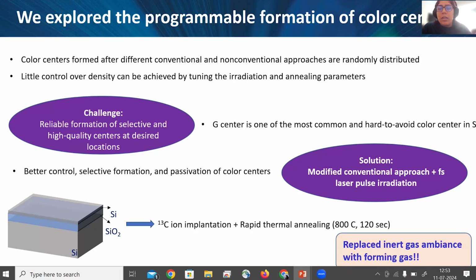What we have done differently is that during the thermal annealing process, we have changed the annealing ambience. People have been using inert gases like nitrogen or argon. But what we have done is used forming gas, which in our case is 10% hydrogen and 90% nitrogen. So essentially we introduce hydrogen in the lattice during the annealing process.